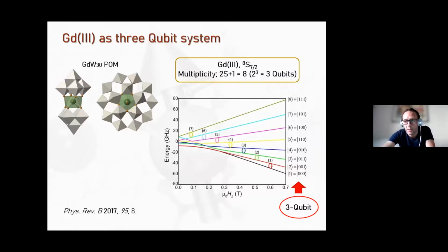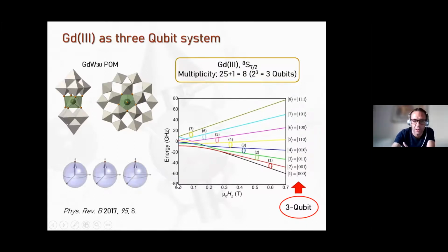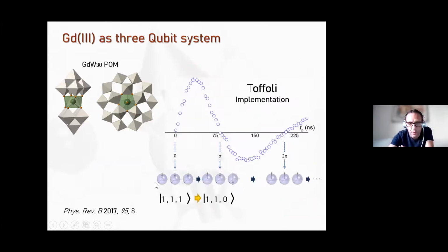And so in this case it would allow us to realize 3 qubits within one single metal, because these 8 states produce the computational basis of 3 qubits. So these are these 3 qubits, and for example, we can use these to realize 3 qubit quantum gates. One of them is called Toffoli, or controlled-controlled-NOT, which flips the spin of a target qubit if the first 2 qubits are in the state 1. And from these experiments using pulse EPR, we can see that indeed on this resonance we can put our system in any of the possible quantum superpositions. So this coherence and these manipulation abilities were demonstrated in this paper not so long ago.